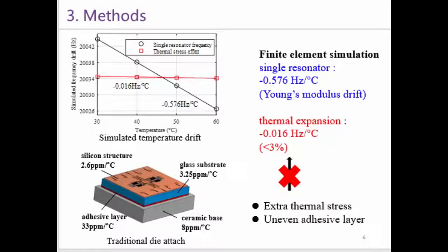However, this result will be affected by the traditional die attach process. We packaged the glass substrate on the ceramic base. The expansion of the adhesive layer will generate extra thermal stress. And the adhesive layer is often uneven. So the simulated results will be affected.